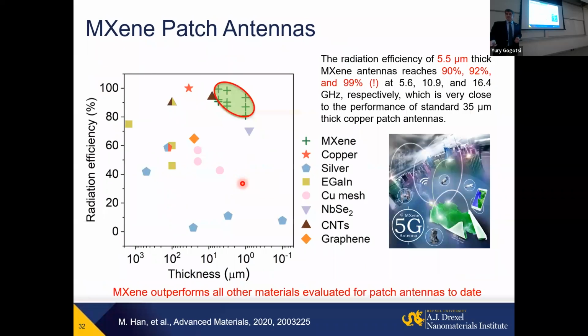But what is important, they give you up to 99% of the radiation efficiency of copper antennas, while being about 10 times thinner and lighter, and again, printable on any surface, flexible, bendable, and so on. You can use them also as a sensor because as you bend the antenna, it changes the frequency, or if you stretch it, for example in a textile antenna. So you can go this way.